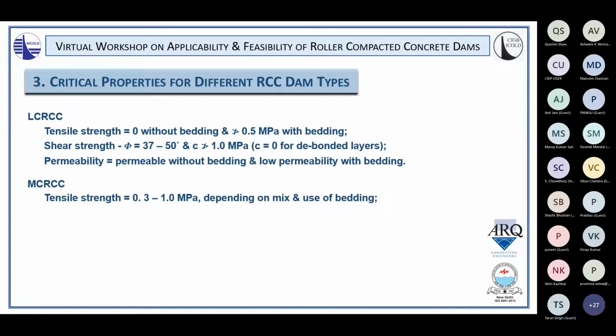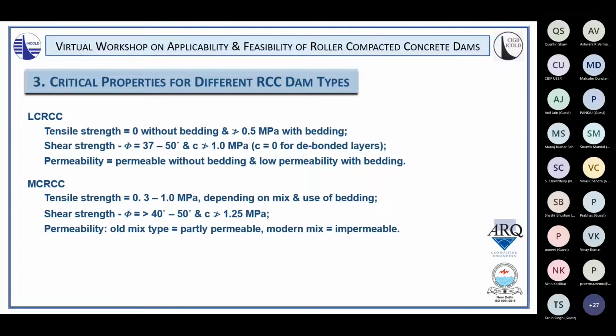The medium cementitious RCC, tensile strengths between typically 0.3 and 1 MPa, depending on the mix approach and the use of bedding between layers. Shear strengths for this with friction angles of the order of 40 to 50 degrees, and cohesions limited to perhaps 1.25 MPa. On the old type of this type of mix, you'd be looking at partly permeable, and realistically you wouldn't be able to be certain of impermeability without a bedding layer between the placement layers, but a modern mix can be designed in this type of RCC for impermeability.